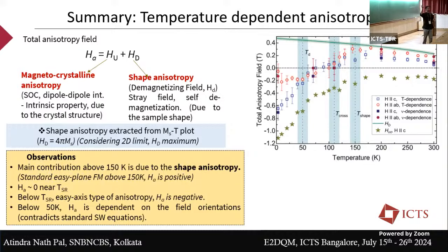I told you these models. What has been used to fit this data is the uniaxial ferromagnet. Okay, using this model, you can fit the data and you can see there is a deviation, and that means the present theory cannot explain this data. So this deviation cannot be explained below 50 Kelvin.